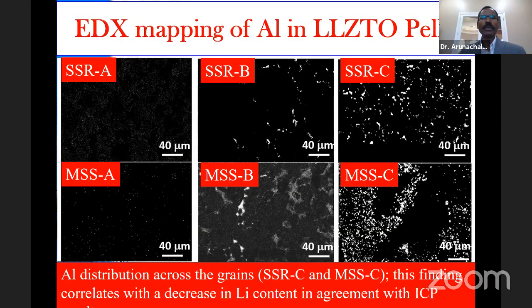This was to make sure that aluminum is there everywhere for the pellets sintered in alumina crucible. You can see this here in B, and also for C, because of the alumina crucible along with the alumina powder as a sintering aid. So aluminum gets distributed throughout the grain for both the solid-state reaction-based and molten carbonate-based powders. This certainly correlates with the compositional verification carried out by ICP, that is, a lower amount of aluminum occupying the lithium sites.